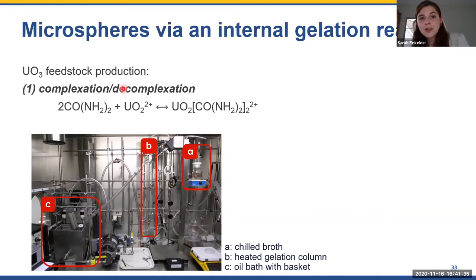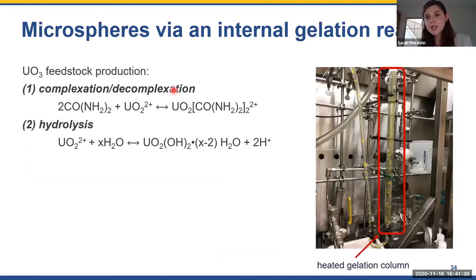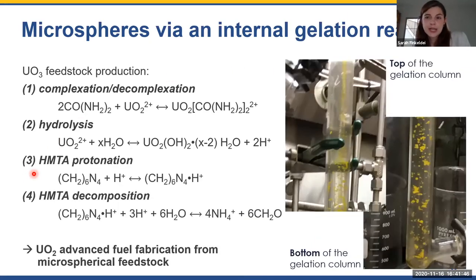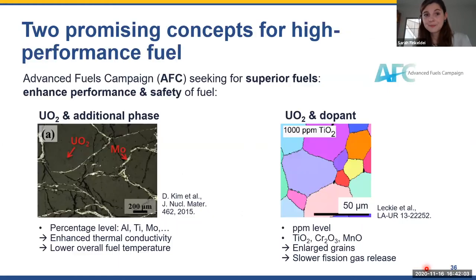In the cold, uranyl gets complexed by urea. And once it hits the top of the gelation column, the reverse reaction occurs, followed by hydrolysis, which causes the hexamethylenetetramine to be protonated and finally to decompose, where ammonia is released, which increases the pH in our droplet. And thus our liquid droplet solidifies while it's on its way down in the gelation column, and we obtain the UO3 microspheres.